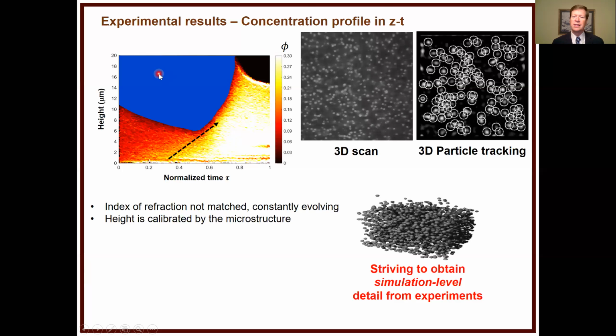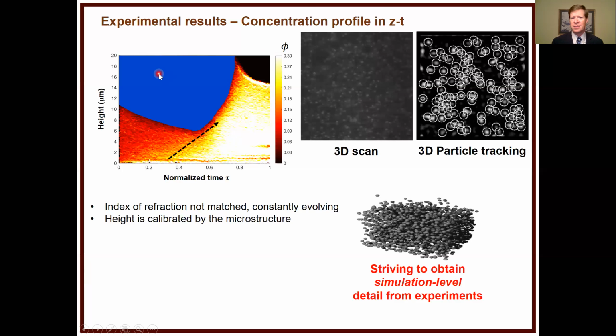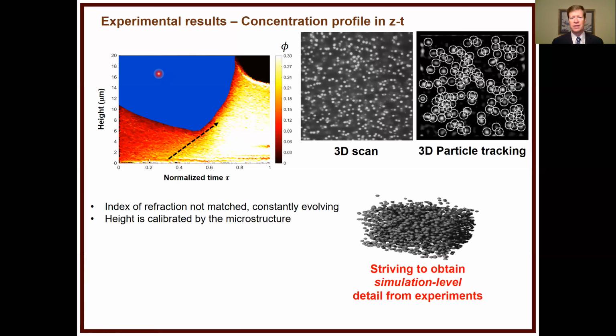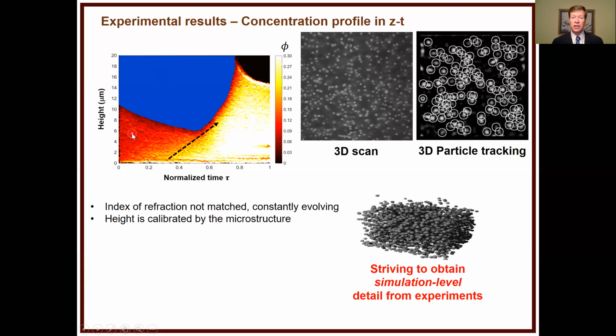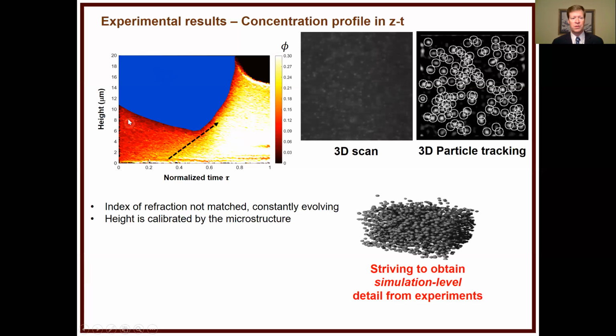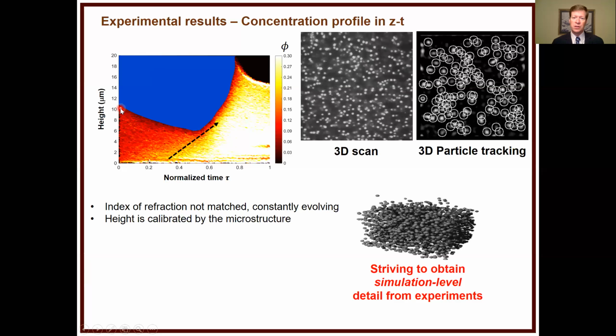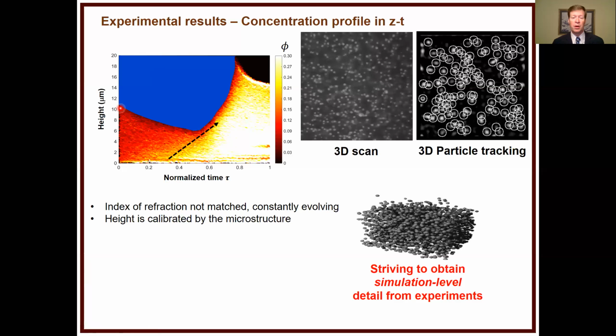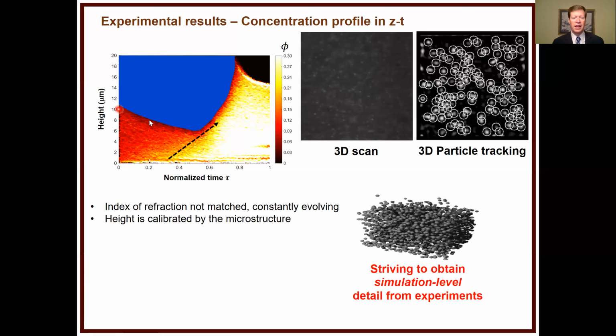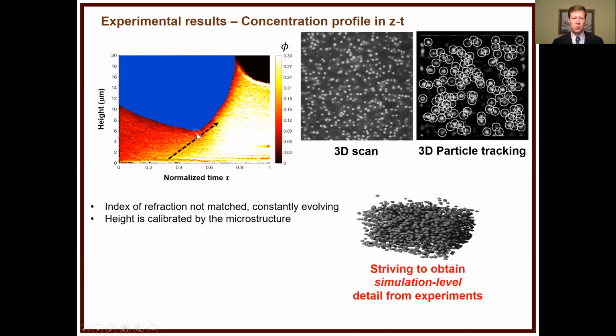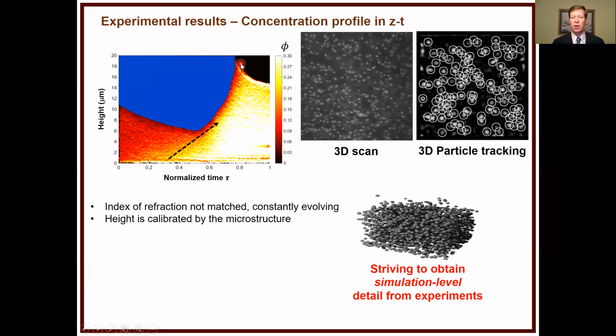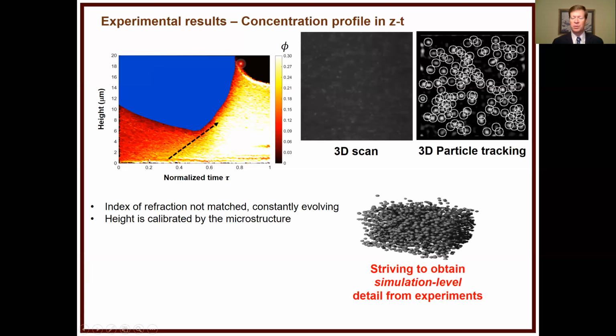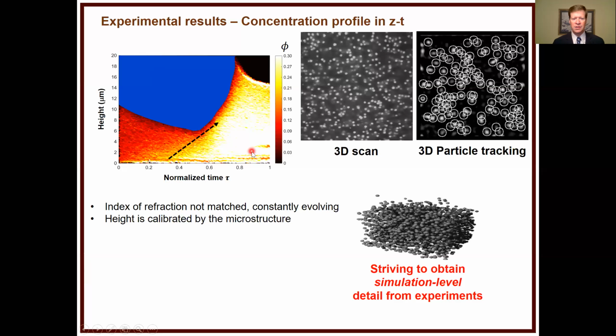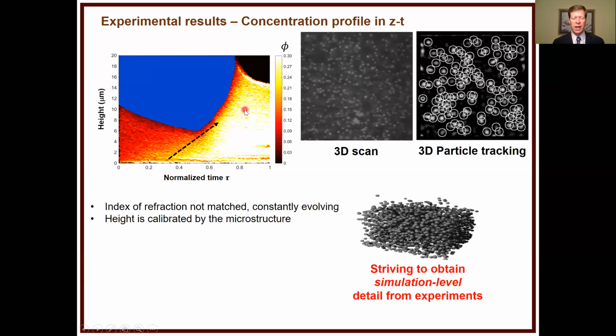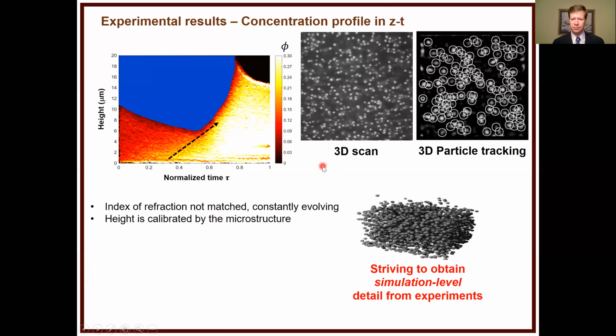The blue area is simply where we cannot properly index match the particles with enough confidence to locate them. The index matching changes in time. If you start with a certain system and it's drying, you're losing solvent, the polymer is becoming more concentrated, and the particles are becoming more concentrated. As you go, the index matching gets worse and then much better as the polymer gets really concentrated between all the particles. So we have this ability to take average scans and get our concentrations.